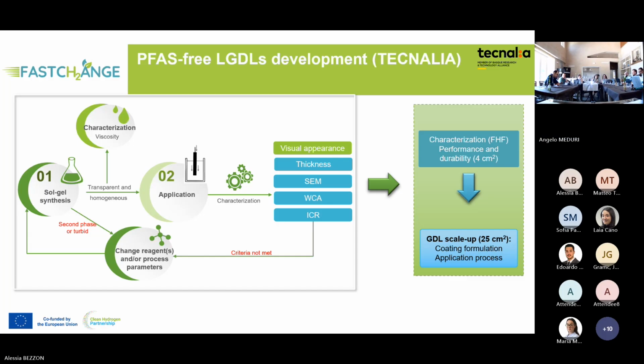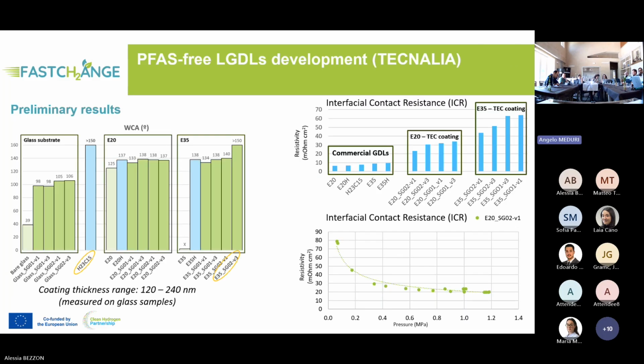This is just some preliminary results to show. On the left you can see the water contact angle. This is just of the glass substrate to check that our coating is indeed hydrophobic, and indeed we reach more than 90 degrees. And then the blues are three commercial